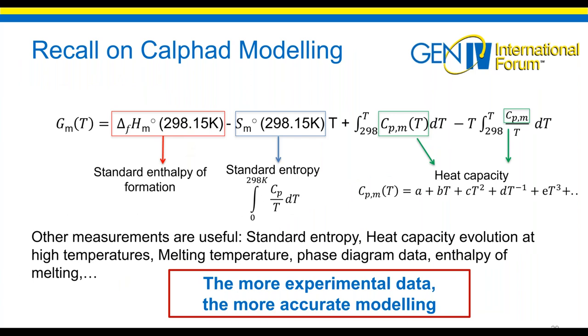So now we'll just do a quick recall on the CALPHAD modeling. So you can find again the G function, but expressed differently, like with the standard enthalpy of formation. So here is the H term, and this is what we measured with our quaternary compounds. You have also the standard entropy, so the S term multiplied by T, and also what we call the heat capacity.